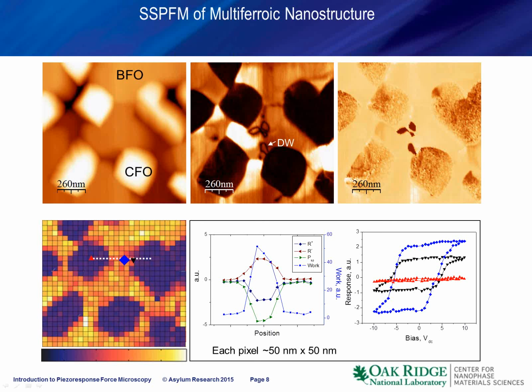Interestingly, though, if we look at the variability of the switching behavior across the surface, in some sense it is trivial. So the response loop in the black point, which is on the boundary between BFO and CFO, is just a half loop of the BFO phase. Because when we switch polarization, the domain can grow in the ferroelectric phase, but it cannot grow in the ferromagnetic phase. So no surprises here, and at that time it was a little bit disappointing. However, in many cases, life can be considerably more interesting.